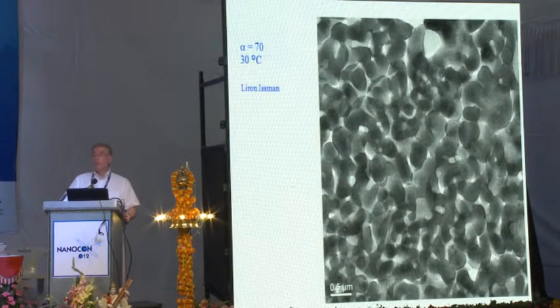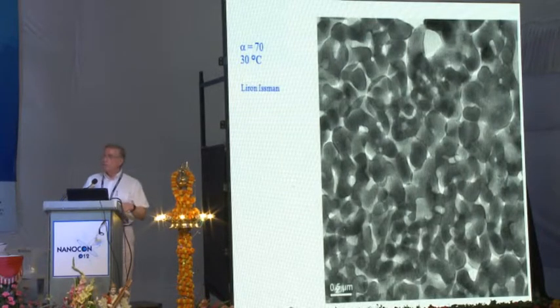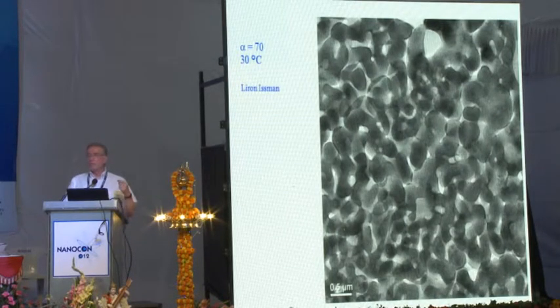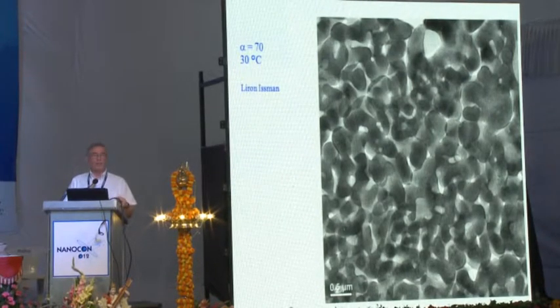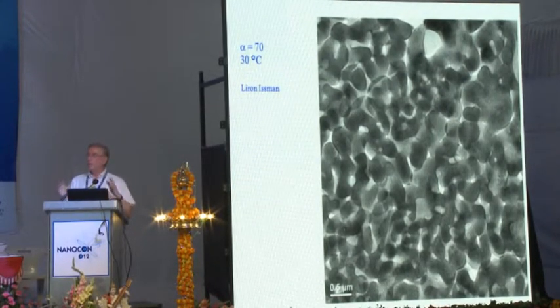And this is the bicontinuous one. And in fact, that we can do this by two different methods and get the same structure really indicates that we have been successful to capture a real object and not an artifact. So whenever we can, we use more than one technique.